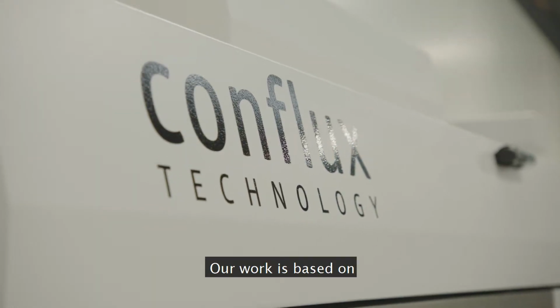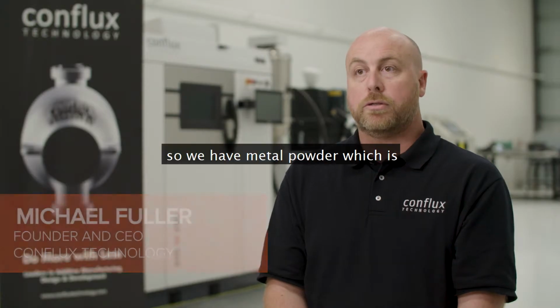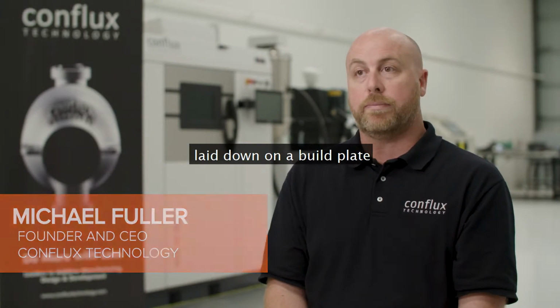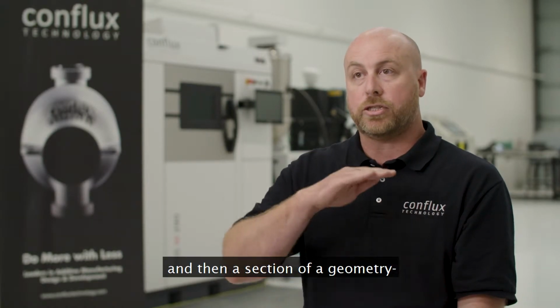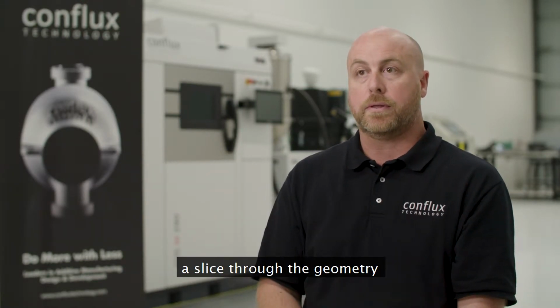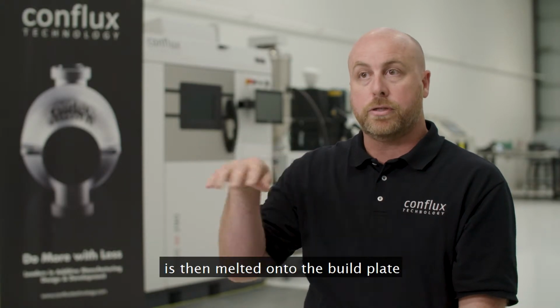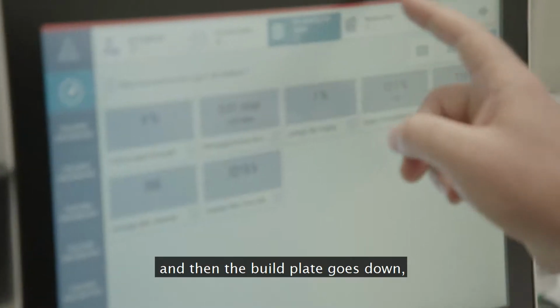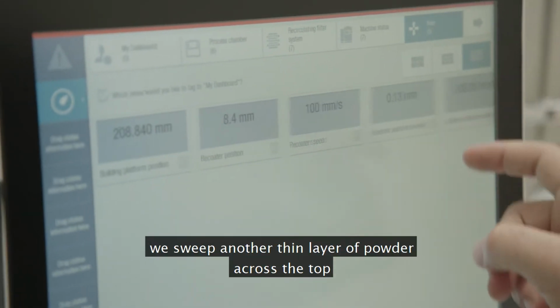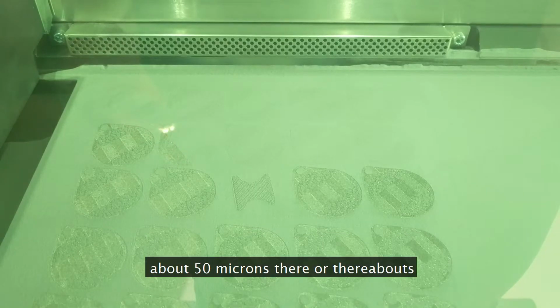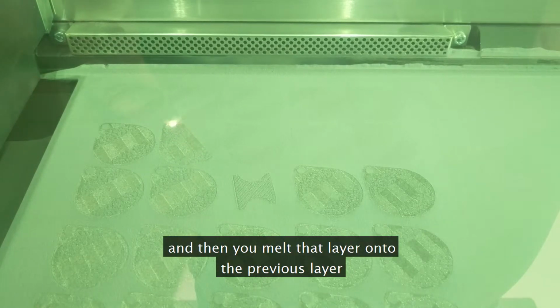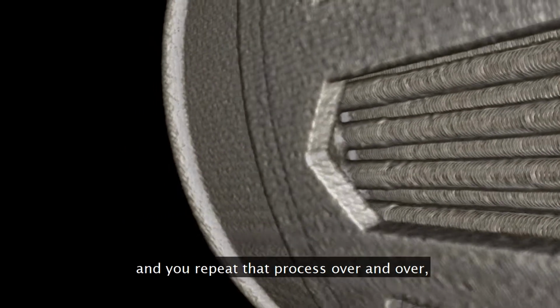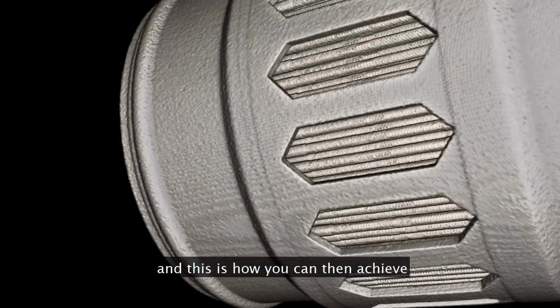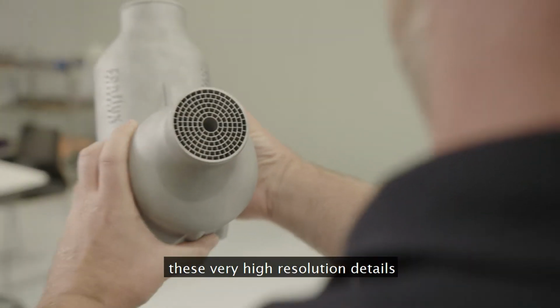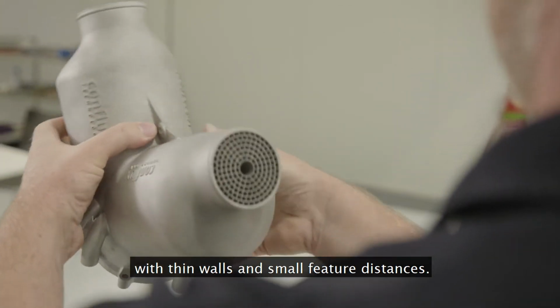Our work is based on what's called powder bed fusion. So we have metal powder, which is laid down on a build plate, and then a section of a geometry, a slice through the geometry, is then melted onto the build plate. And then the build plate goes down, you sweep another thin layer of powder across the top, about 50 microns there or thereabouts, and then you melt that layer onto the previous layer, and you repeat that process over and over. And this is how you can then achieve these very high resolution details with thin walls and small feature